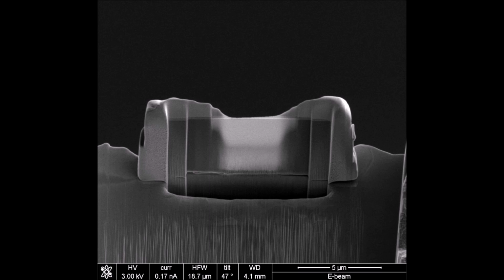So one thing to consider is, what if your goal of doing the analysis, for example, is to do weak beam dark field imaging? Well, weak beam dark field imaging is kind of interesting in the sense that if the sample's too thin, it actually becomes somewhat counterproductive. So you always have to start by asking the question, what am I trying to learn by doing TEM? Generally speaking, yes, you're trying to get the sample as thin as possible, but again, maybe, maybe not, depending on the analysis that you are trying to do.